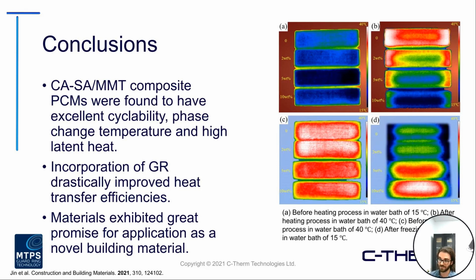The graphene additive really improved the heat transfer efficiency. While you do need to maintain that heat storage, you also need to make sure it is transferring efficiently within the bulk, and that's what the graphene really showed and accomplished here. In the end, they concluded it exhibited great promise for application in a novel building material.